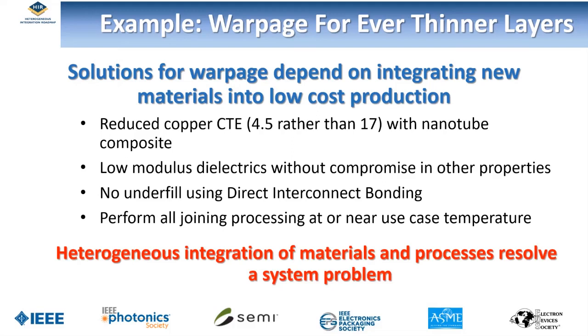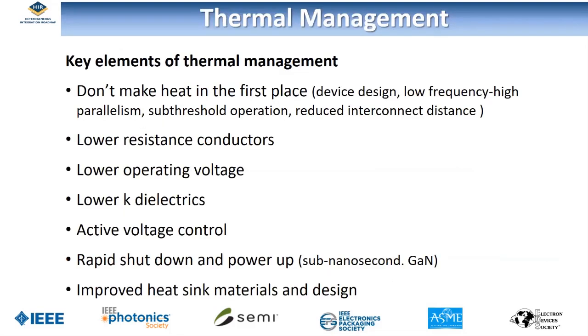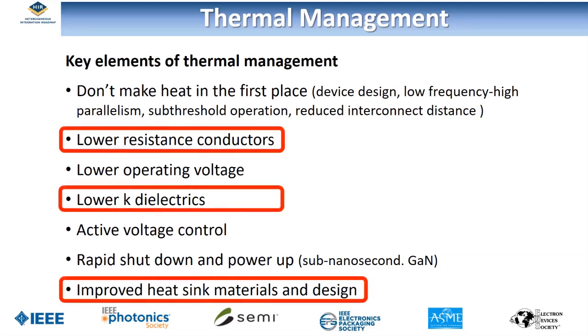resolves a system problem. Key elements for thermal management: don't make heat in the first place. Lower resistance conductors, lower operating voltage, lower K dielectrics, active voltage control, rapid shutdown, sub-nanosecond, which you can do with gallium nitride, and improved heat sink materials and design. But the three most important ones are lowering resistance, lowering dielectric constant, and improved heat sinks. Next slide, please.